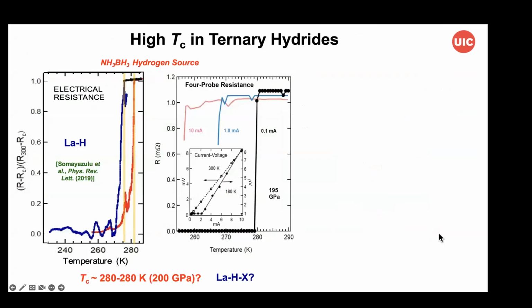So let's now move on to other systems, coming back to the lanthanum hydride in the work that we did showing high Tc in lanthanum decahydride. We found in a number of experiments where we used ammonia borane as a starting material that one sees variable Tcs or variable onsets of conductivity depending on the conditions of the synthesis. And these experiments were not complete four-probe measurements, so we had to normalize the resistance. We didn't have a zero resistance state after the onset of conductivity. But nevertheless, onsets that varied from 270 up to 290 Kelvin.